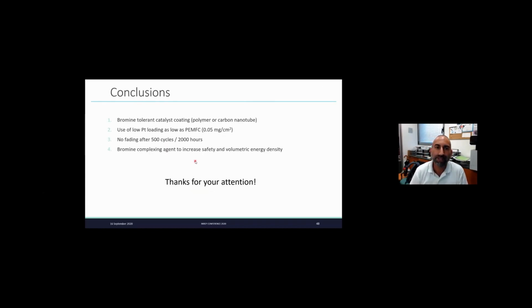My conclusion is that we managed to do some bromine tolerant catalyst coating so that we can still use platinum with very, very low loading. We can go down, and I hope that we can go down to 0.05 milligram per square centimeter, which is about what PEM are doing today. We don't see any fading, and we can use bromine complexing agent for increasing the safety and the energy density.